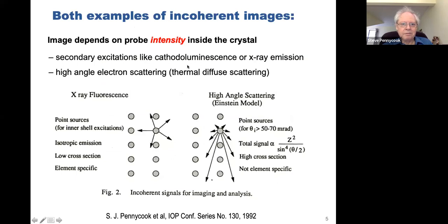And thinking about it, of course, the high angle scattering is generated incoherently by hitting the atoms. It's thermal diffuse scattering, so it's generated incoherently. It depends on the intensity of the beam hitting the sample, which is exactly what cathodoluminescence was. These are incoherent signals. Well, okay.